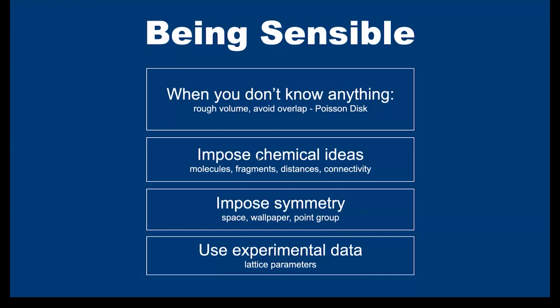You can do some of the work for the algorithm in the way that you're building the molecules first, and then allow those molecules to arrange themselves into other configurations. And in the solid state concept, molecules could be fragments of crystal structures. It can also be very useful to enforce different distances between different pairs of species to capture, say, for example, in sodium chloride, that sodium doesn't want to be next to sodium, but it does want to be next to chlorine. You can impose those distance constraints, and you get a lot of chemistry already hard baked into your